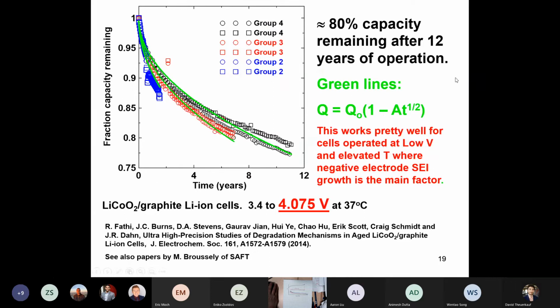Okay, so if you have a situation where you only have capacity loss due to the thickening of the negative electrode SEI, then the capacity of the cell should be the initial capacity times 1 minus a constant times t to the power half. Okay, so these data here are described in this paper by Riza Fathi, and it's from 2014. So these are lithium cobalt oxide graphite cells. They're only going to 4.075 volts. And at this low voltage, positive side reactions with the electrolyte are very minimal. It's at 37 degrees C.